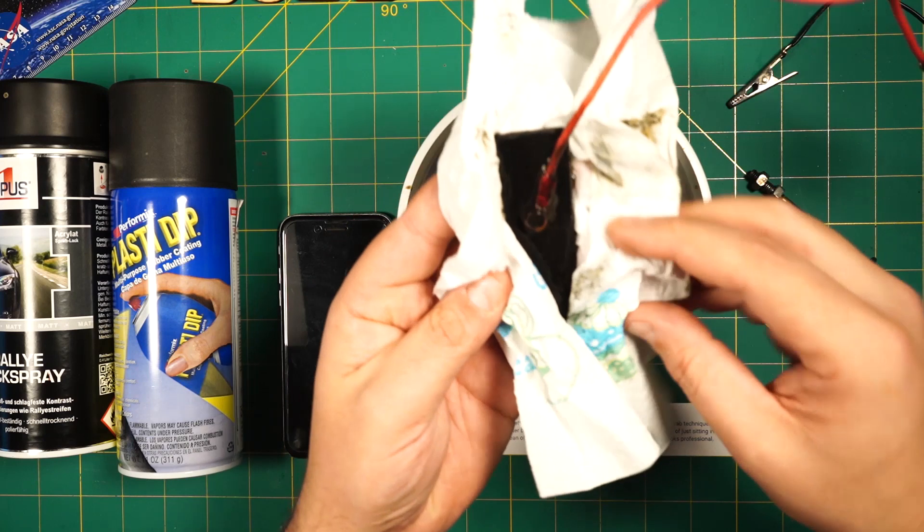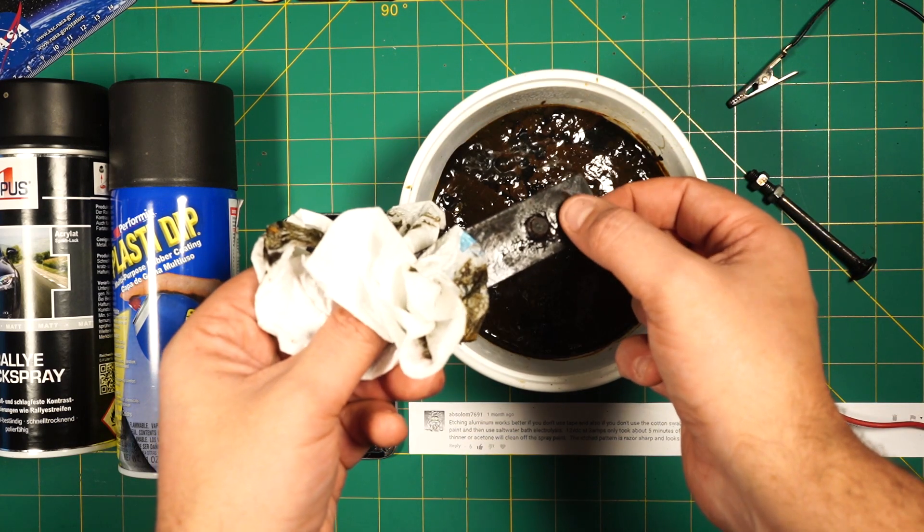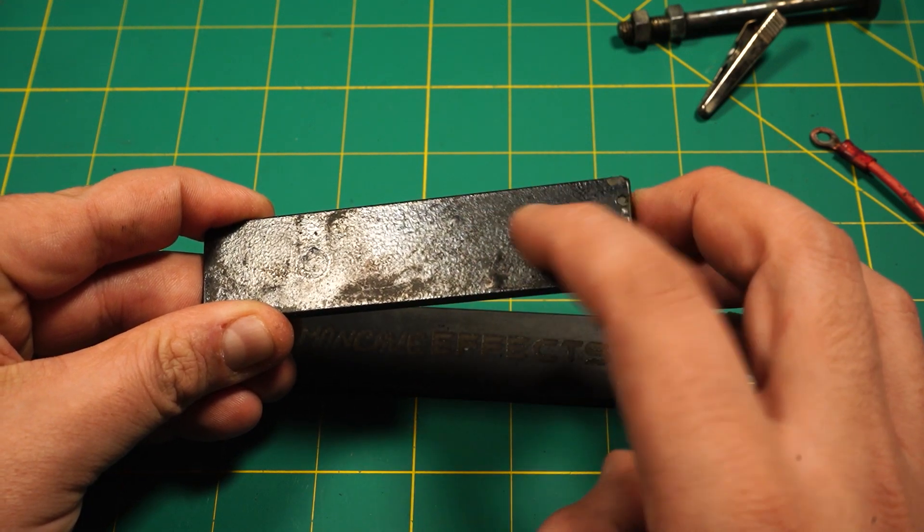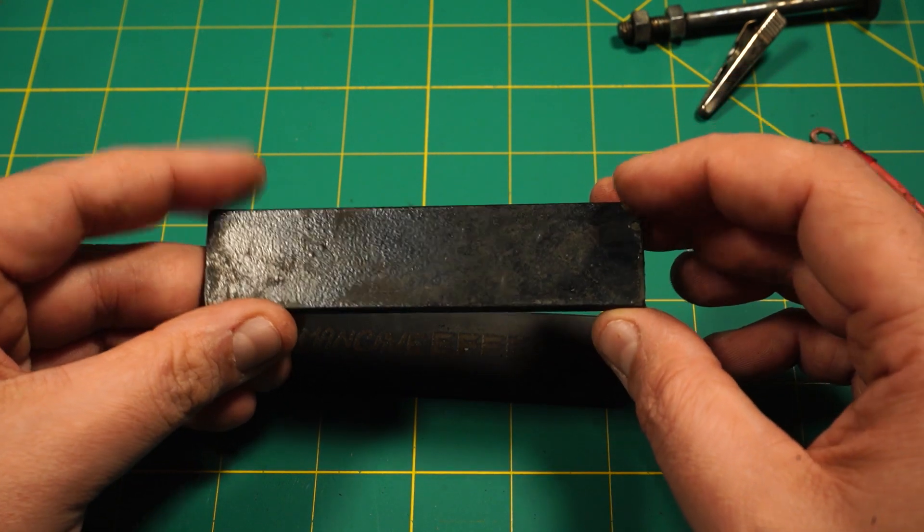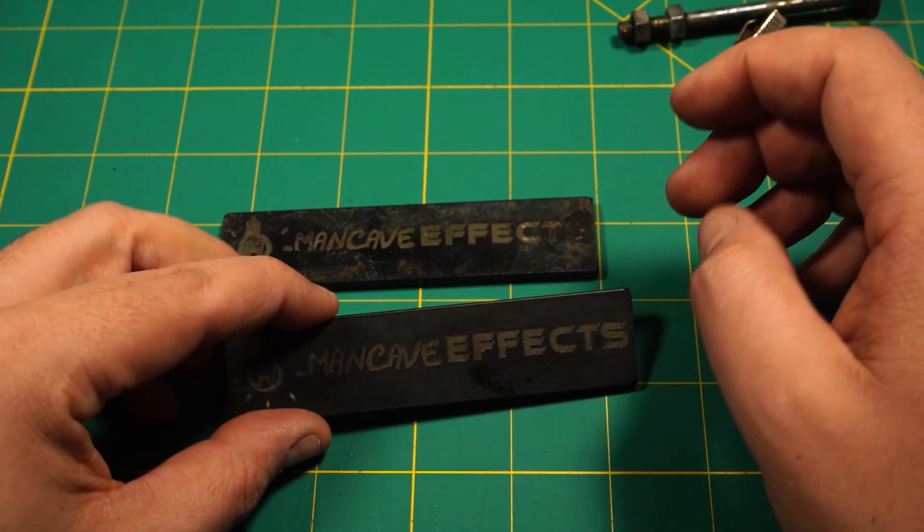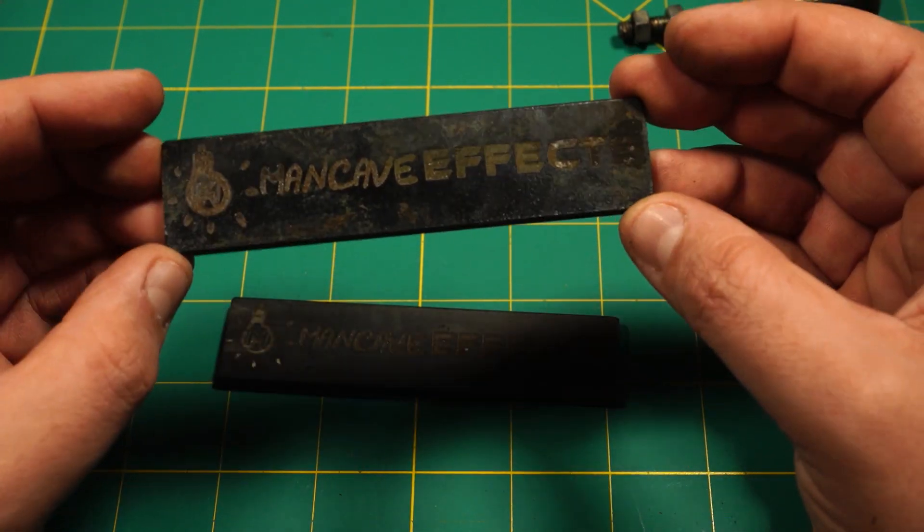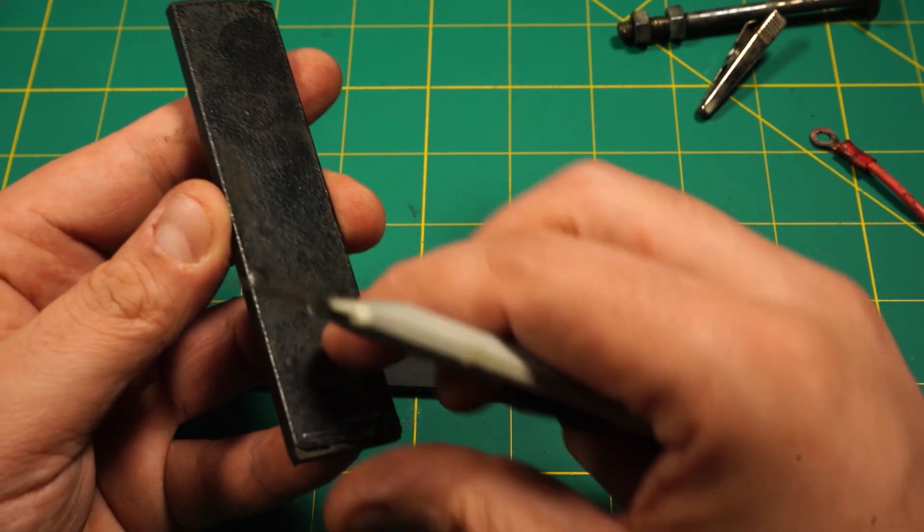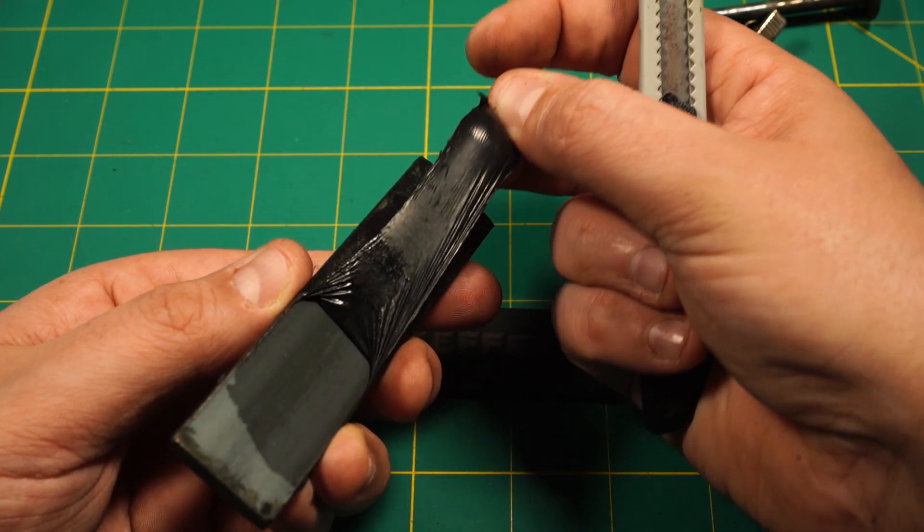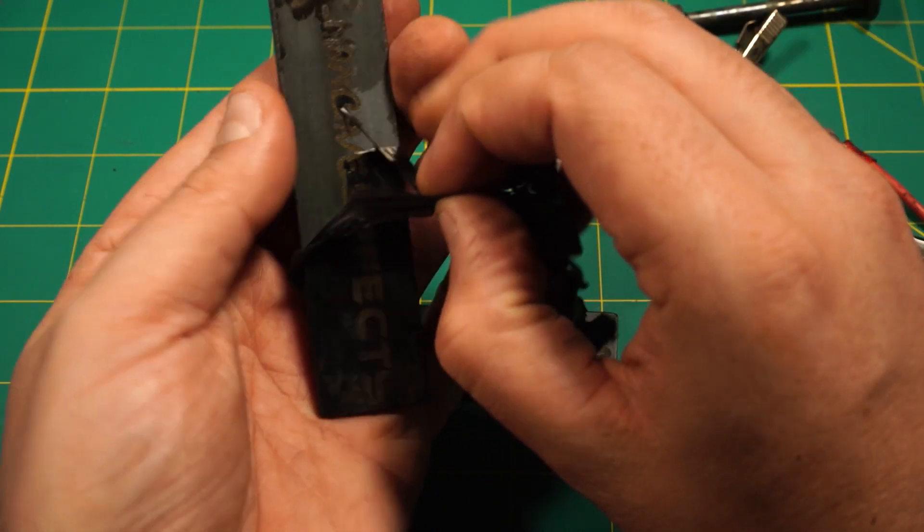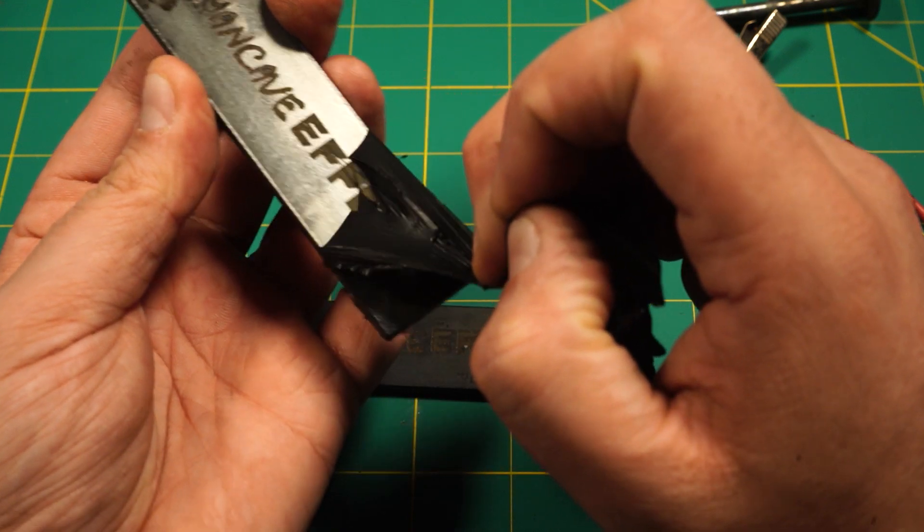Both experiments have etched pretty well. As you can see, the Plasti Dip bubbled up on some spots. I guess this is because of gases that build up underneath while doing the etching. Now it is a matter of cleaning off the spray paint and Plasti Dip. For the second, it is supposed to be a matter of simply pulling off the skin-like film. Wow! This comes right off, like a charm! Very impressive!